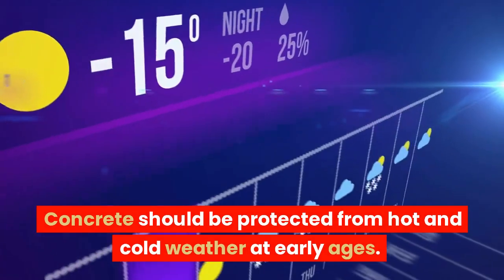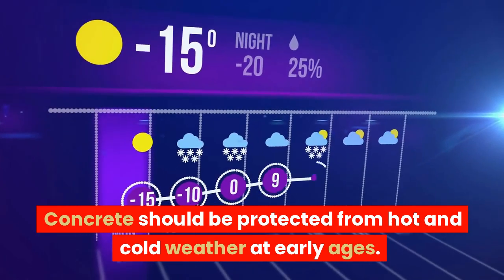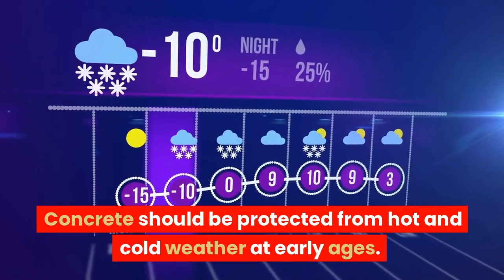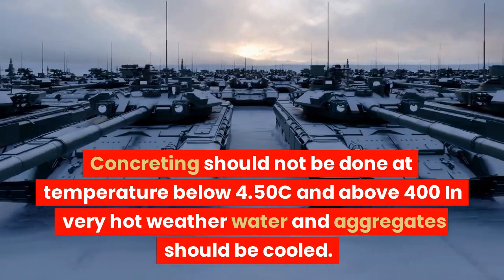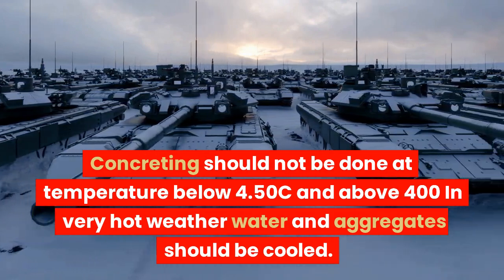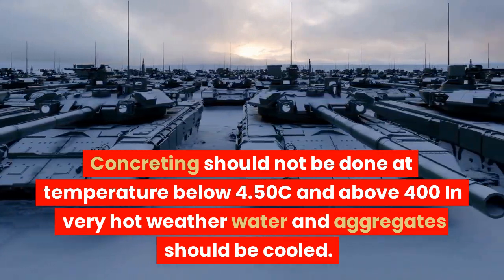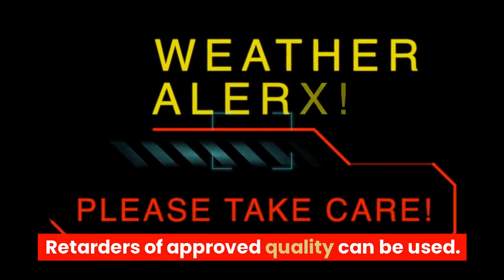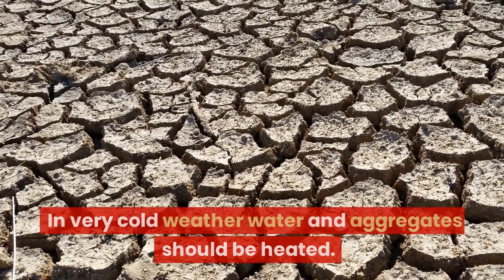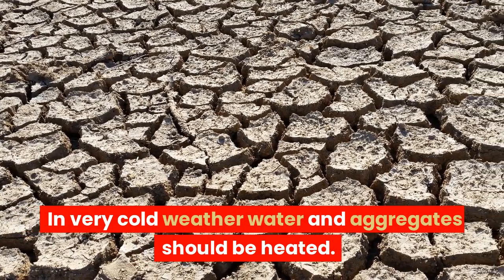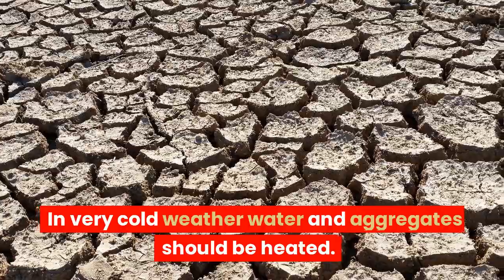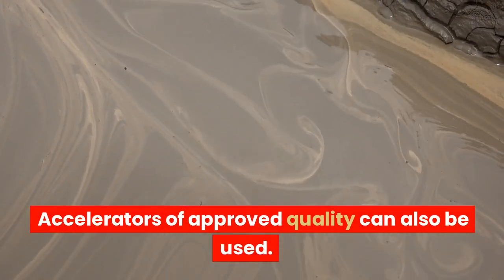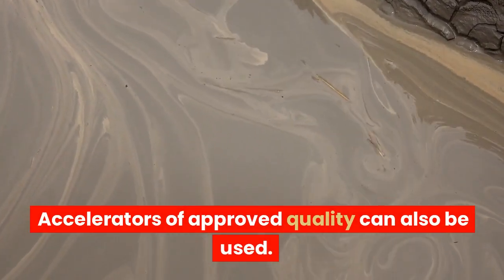Concrete should be protected from hot and cold weather at early ages. Concreting should not be done at temperature below 4.5°C and above 40°C. In very hot weather, water and aggregates should be cooled. Retarders of approved quality can be used. In very cold weather, water and aggregates should be heated. Accelerators of approved quality can also be used. 3.